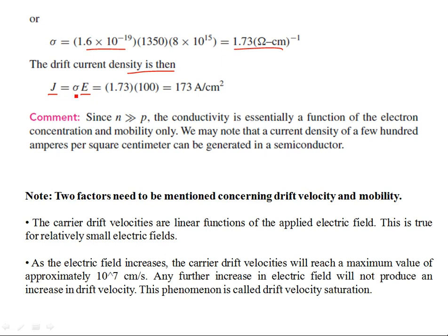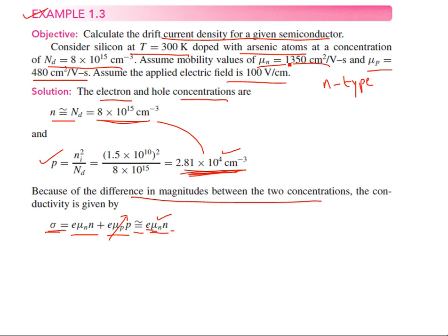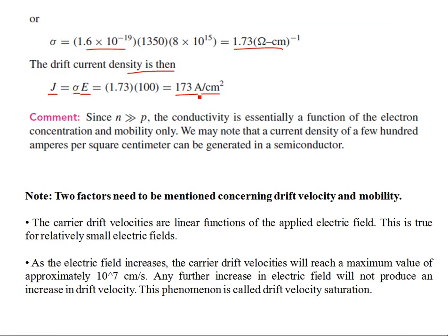We have the conductivity, we have the electric field, so the current density is about a few hundred amps per centimeter square, but still respectable. For a given applied E field of 100 volts per centimeter, at room temperature this tends to produce a respectable current of a few hundred amps per centimeter square. So this E field is enough to generate a drift current density of 173 amps per centimeter square in an N-type semiconductor material.